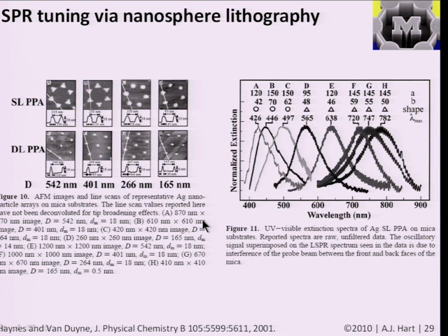And they, for example, have characterized the topography of the substrate, basically around where each sphere was, where it would be contacting another sphere, like here and here. In between those two contact points, there's a particle. And you can see for these different conditions, the size of the particle varies, and also the shape of the particle varies when you go from the single layer process to the double layer process.